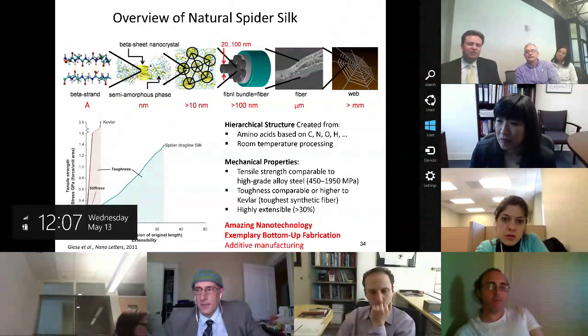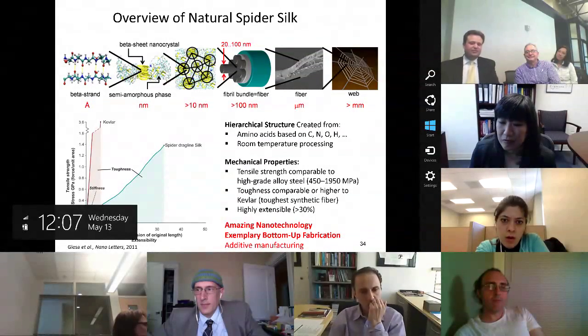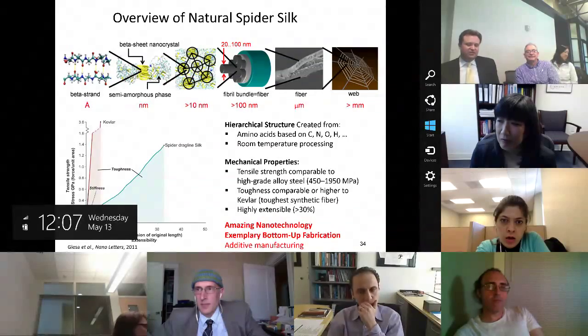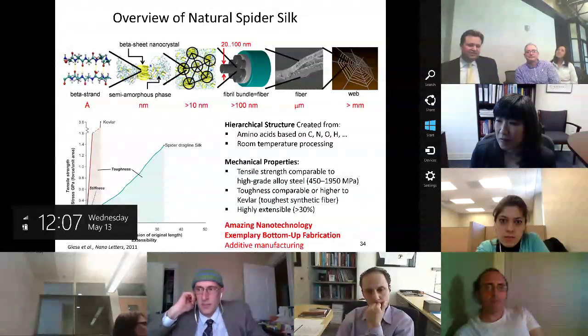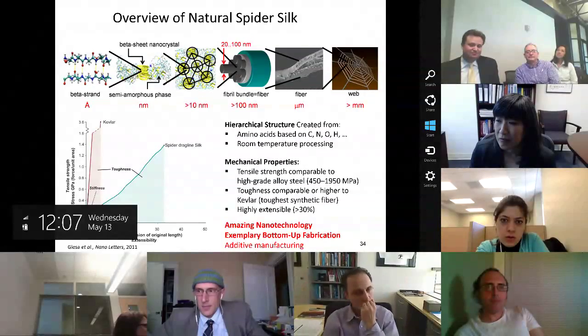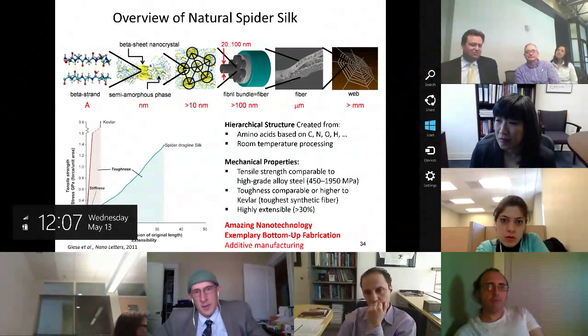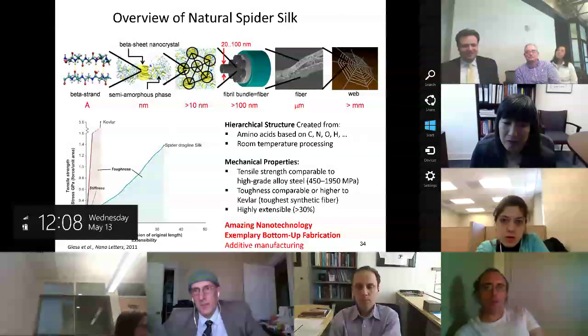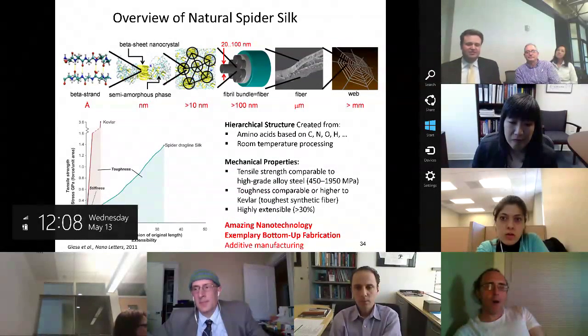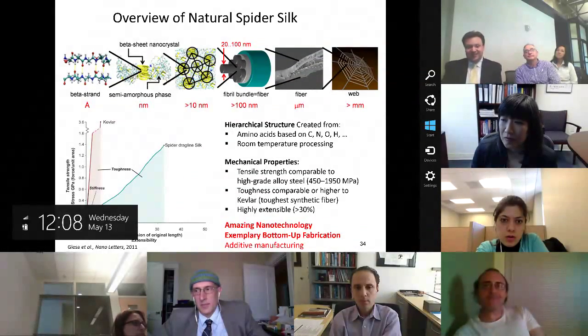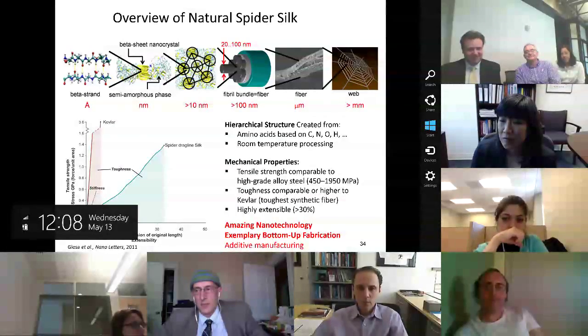Now if you go into a different material, and we haven't talked about elastin today, but this is something else in the project we're exploring in early stages, it's not going to be as easy for elastin because the scale separation is not as clear. Here in silk we're dealing with patterns where we can group amino acids very effectively, extract parameters, and find properties between the beads. In the case of elastin, the separation of scales is smeared out much more significantly, and a three amino acid parameterization for elastin would not be possible.